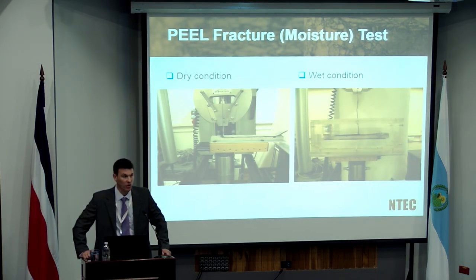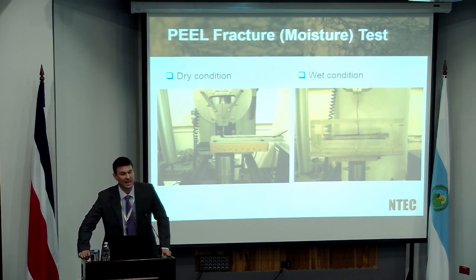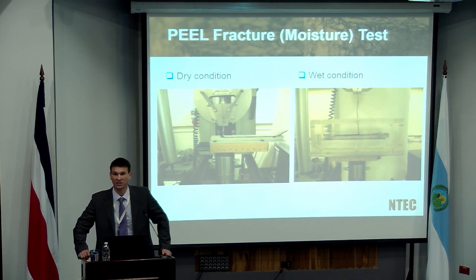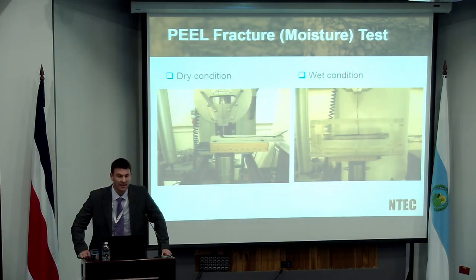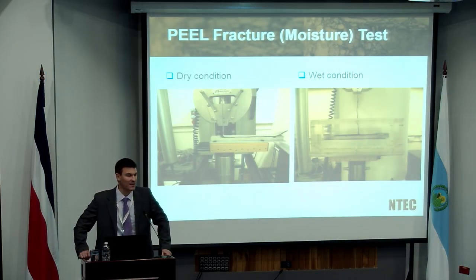So that's only half the story, though, because that's only trying to understand adhesion in terms of the dry condition. We talked right at the beginning about the fact that we are really talking about moisture damage, and therefore exactly the same as when we use the surface energy and intrinsic adhesion calculations where we had to have a dry versus a wet. We've got to do exactly the same thing for the peel arm. And that causes us a problem because that's not straightforward. So we tried a number of different techniques. I'm going to explain three of them here.